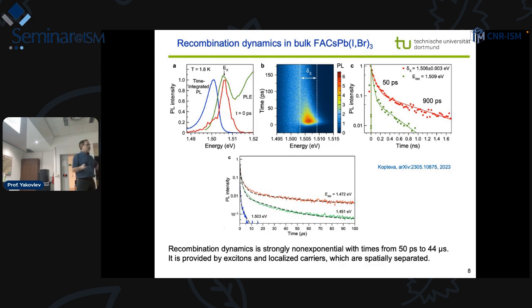But if we use time resolution, a streak camera, we excite with 100 femtosecond pulses, and here measure on the image how the photoluminescence decays with time. And we measure on the very first time moments, the first 20 picoseconds. The photoluminescence will be here. So excitons recombine very fast, and then the recombination is shifted to lower energies and is contributed by excitons, bound excitons, electron-hole pairs. So we're still not very sure what the processes contributing here are. And one can see that the recombination dynamics has a fast component of 50 picoseconds, which turns to 900 picoseconds.